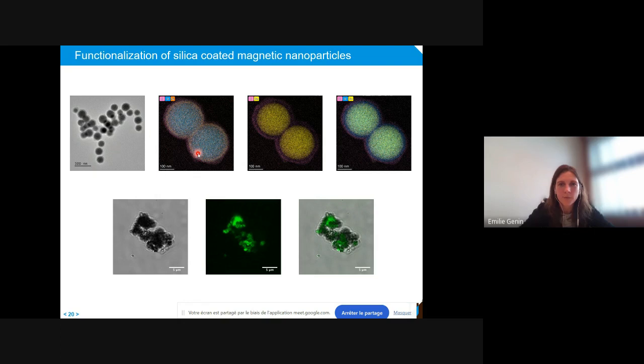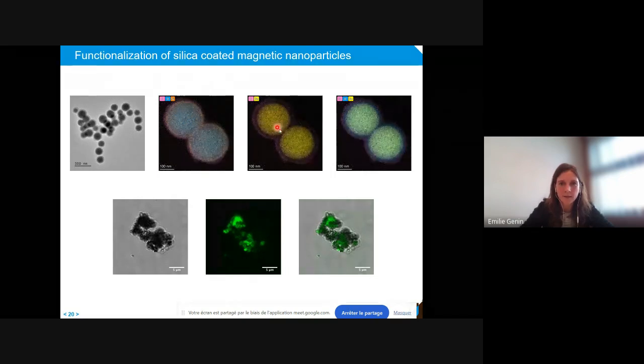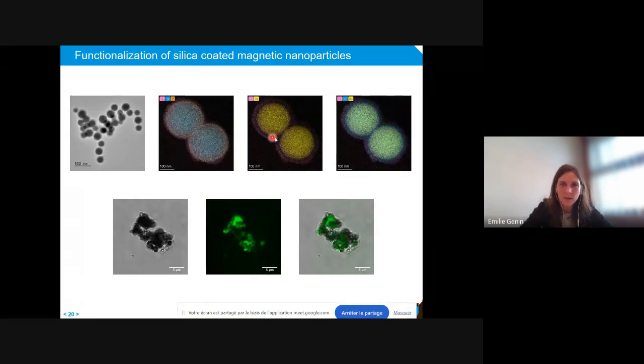To go further in the analysis, we also did microscopy coupled with X-ray spectroscopy to map the different atoms. Here, with the carbon-oxygen-silicium, you can clearly see the inorganic parts, the magnetic nanoparticles. And if you check with the carbon and only iron, you can see that the carbon - the organic part, the organic ligand - is functionalizing the magnetic nanoparticles.